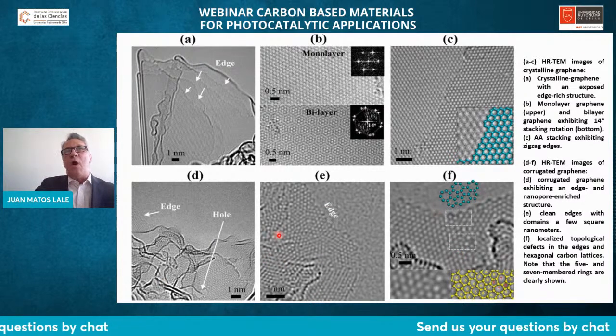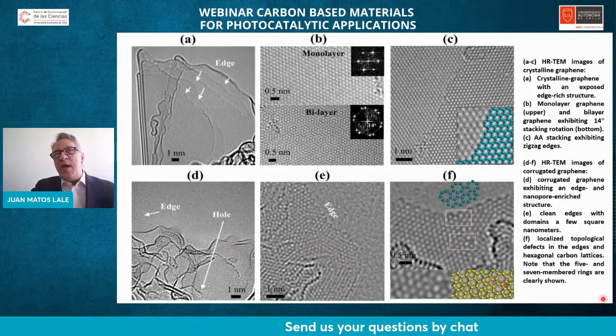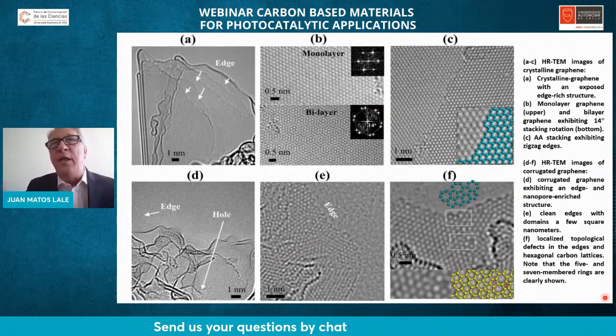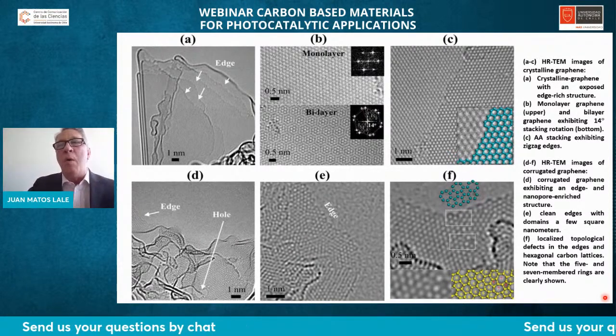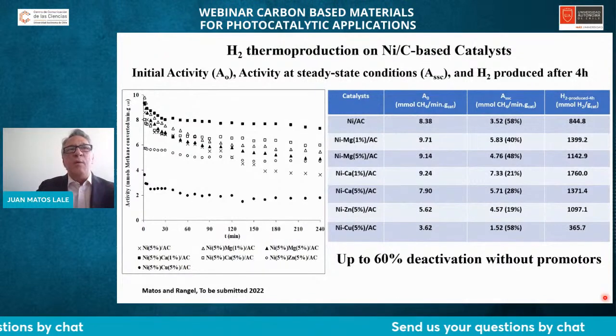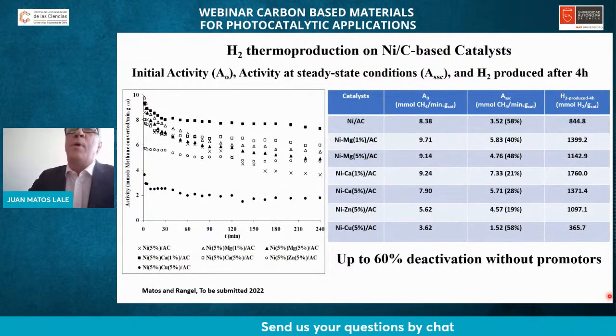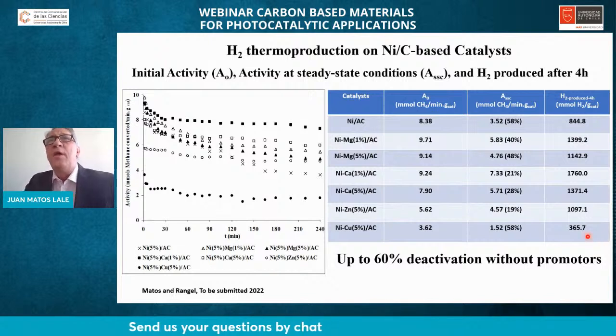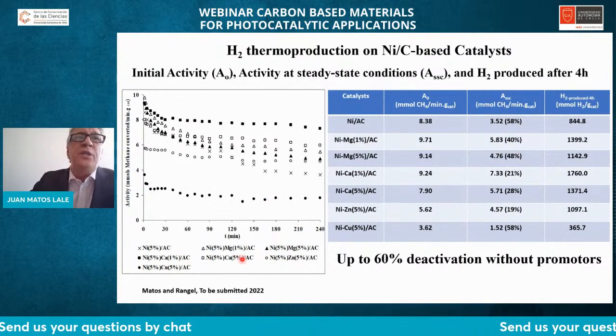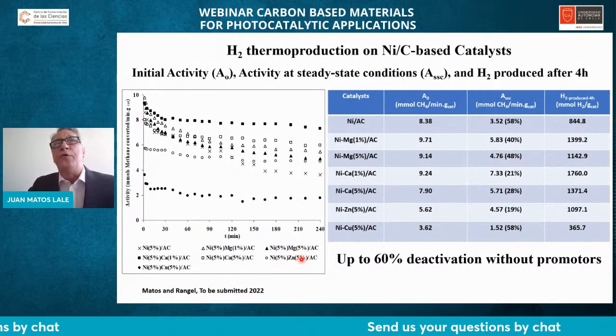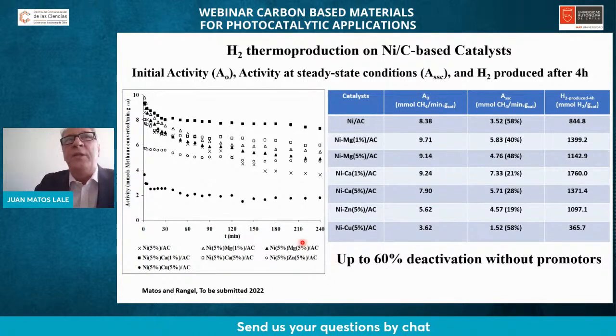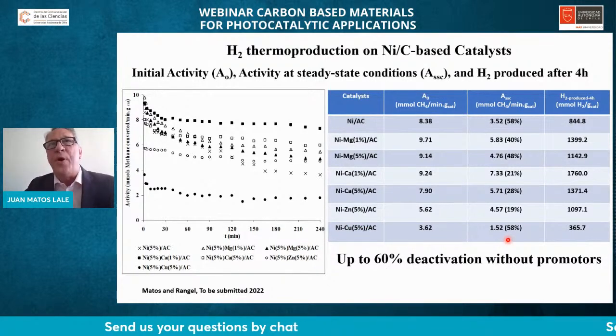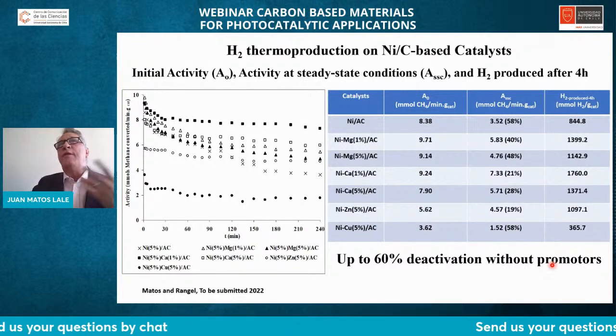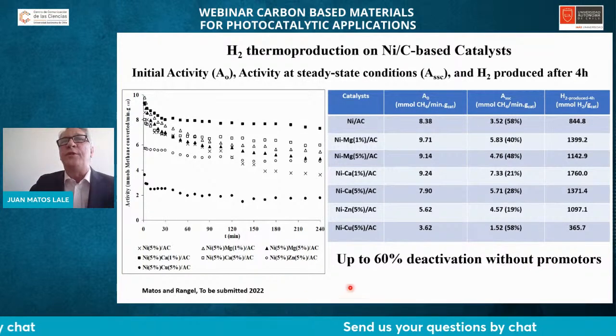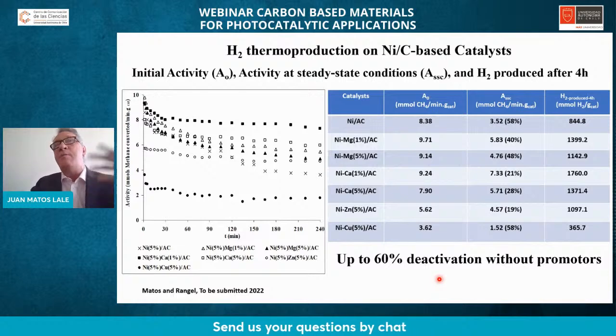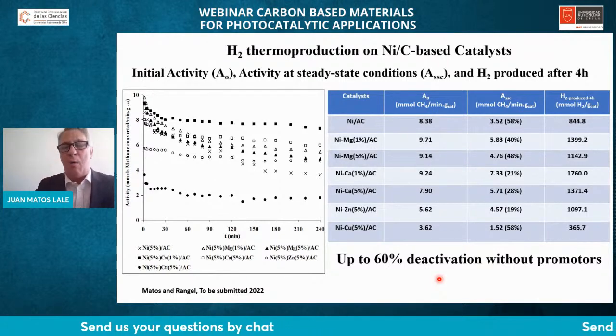In the reconstruction of corrugated graphene materials, we have networks with pentagons, heptagons, and so on. So with this kind of material, we are already obtaining very interesting results in hydrogen production, and changing the chemical nature of the product by using alkaline earth materials, zinc oxide or copper oxide. We are able to control the deactivation. In absence of promoters, the deactivation of the catalysts reached even 60% in only 4 hours.